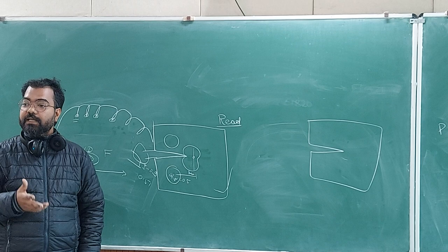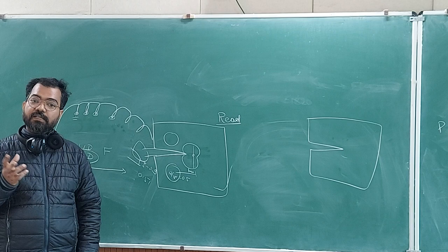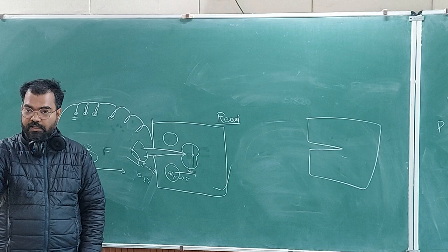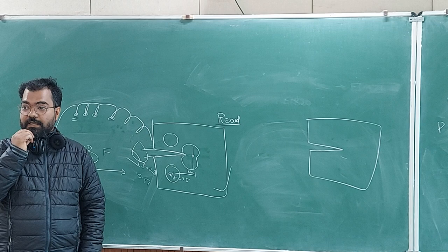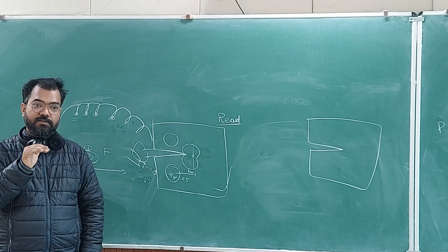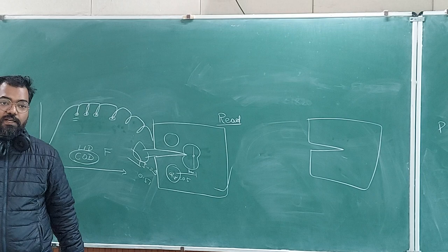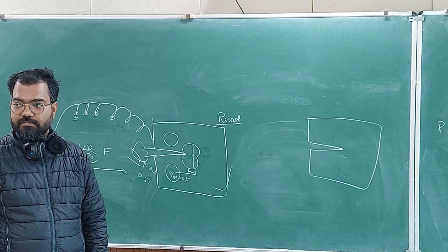Fatigue pre-cracking takes a lot of time, depends what machine you have. So we had a machine which could work at 100 Hz. 100 Hz is very high. You will not get a machine which works at 100 Hz here. Okay, maximum you will get 10 Hz, 20 Hz. So at that frequency of loading, you will have to wait for 2-3 hours for the sample to break. And if it is a 50 millimeter sample, then it will take a very long time to break. Okay, so we'll just stretch it. But the standard procedure is to heat tint it.